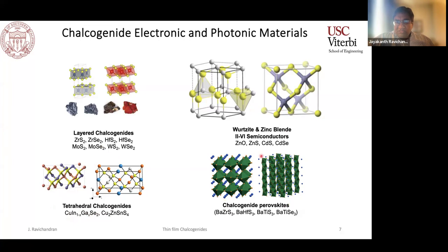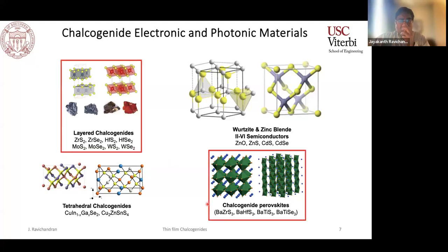Last but not the least, the most recent entrant to this list of chalcogenides is the chalcogenide perovskites and related phases, where you have this ternary alkaline earth metal like barium, transition metals such as zirconium and hafnium and titanium, and the sulfur or selenium on the X side, which forms these octahedrally coordinated structures. So there is a lot of chemical variety, structural variety in these classes. But one thing that you may start to notice is that there are significant challenges even with main group systems in the growth of these materials, and it gets much more perverse when you think about materials that involve transition metals. Why does that happen?